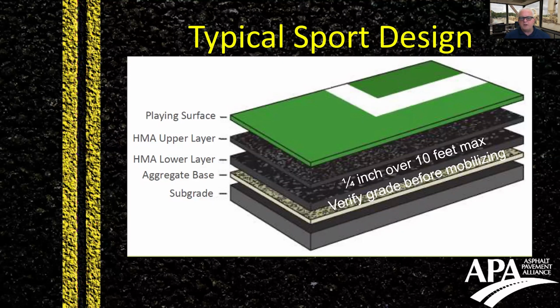The lower layer of asphalt, a typical 10-foot tolerance requirement is 1/4 of an inch over 10 feet, and that's with just a 10-foot aluminum straight edge, no more than 1/4 of an inch of deviation. And then the upper layer of asphalt, it's a tighter requirement. It's 1/8 of an inch over 10 feet with a 10-foot aluminum straight edge, and that's so that you don't end up with any big surface deviation, surface anomalies that affect the use of the court. And then of course you have a playing surface on top of that, might be some type of a coating.